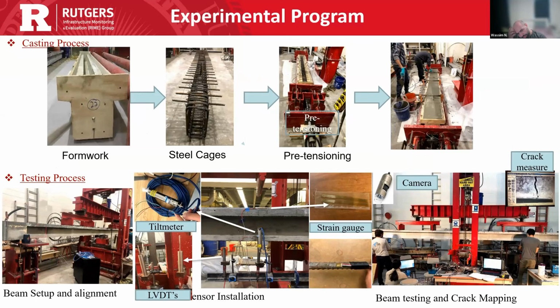Okay, so these are the steps involved for the experimental program: building a formwork, then steel cages, then pre-tensioning. That's exclusively for simply supported beams. It is done in a pre-stressing bed, but for the continuous beam, it is done on the testing setup itself. We use strain gauges to monitor strains, LVDTs for deflection, and tilt meters to measure rotations at critical sections. And we also monitor the cracking behavior using micro cameras.